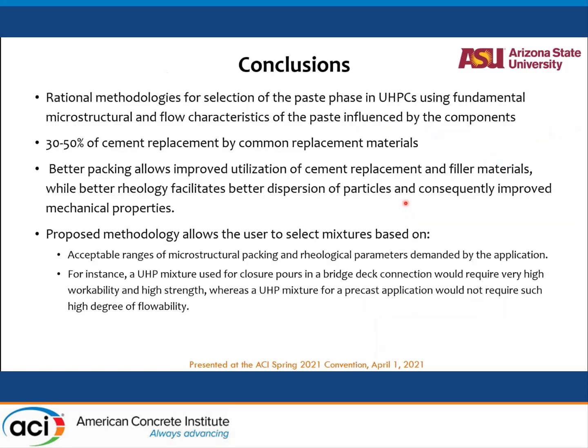So just to conclude, I talked about rational methodologies for selection of paste and aggregate phase using microstructural flow characteristics. One thing that I did not explicitly mention, but you would have seen in the mixture identifier that I've shown, all our UHPC mixtures had up to 30 to 50% of OPC replaced by other cement replacement materials, either by fly ash, metakaolin, and limestone, or silica fume and limestone, or combination of these materials. Better packing allows improved utilization of cement replacement and filler materials, while better rheology facilitates better dispersion of particles and improved mechanical properties, which is obvious.